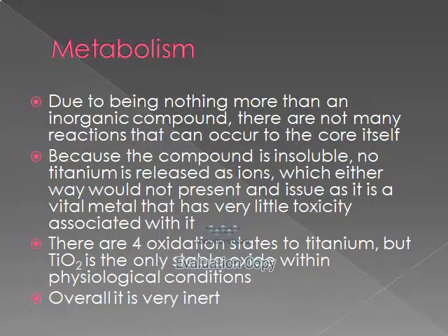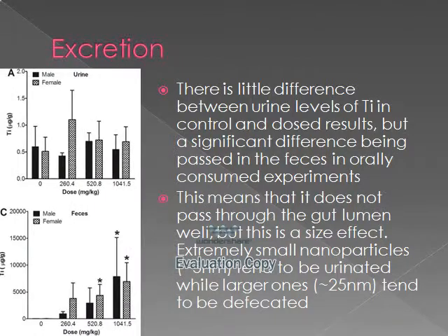There's 4 oxidation states of titanium, but titanium dioxide in the 4+ oxidation state is the only stable oxide within physiological conditions. So overall, for metabolism, titanium dioxide nanoparticles are extremely inert.